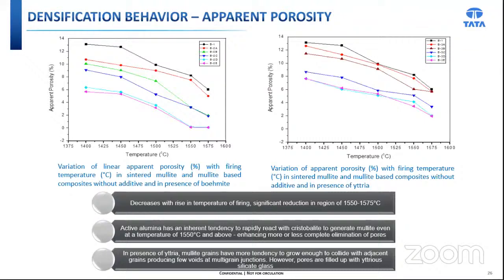Since active alumina in synthetic boehmite has an inherent tendency to rapidly react with cristobalite to generate mullite even at a temperature of 1550 degrees centigrade and above, there is more or less complete annihilation of pores in the sintered compact containing 1.5% boehmite. With the progressive rise in firing temperature and yttria content in the composition, more and more densification occurs with low porosity content, because at this stage enhanced yttrium silicate has been produced, which favors simultaneous lattice and grain boundary diffusion.